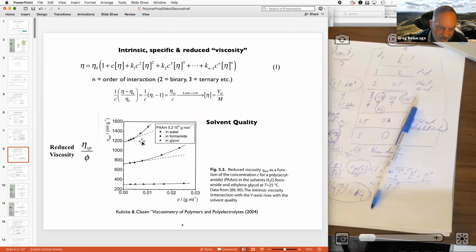And again, depending on how the water sticks in the coil, this hydrodynamic size can change, and definitely changing the solvent with something that hydrogen bonds is going to change the draining capacity of the chain. So you can see that taking this thing as a thermodynamic number is a mistake.